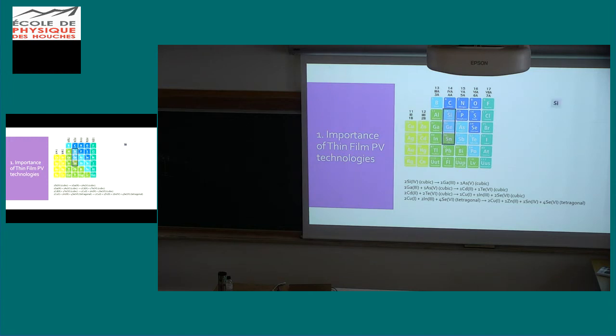So, more concretely, to better understand this, we can really play with the periodic table. If we start with silicon, and move one right, substituting one silicon by gallium and another silicon atom by arsenic, we have gallium arsenide, another very powerful and very nice photovoltaic material. If we move once again, one left and one right, and substitute gallium by cadmium, arsenic by tellurium, we have cadmium telluride. If we keep constant this column and we start to substitute cadmium, one left and one right, one cadmium by copper, one cadmium by indium, and tellurium by selenium, which is in the same column, we have copper indium diselenide. And finally, if we keep constant copper and selenium, and we move one left and one right, indium we have tin and we have zinc, and we form then the kesterite. So of course, this and this have cubic structure, this has tetragonal structure.